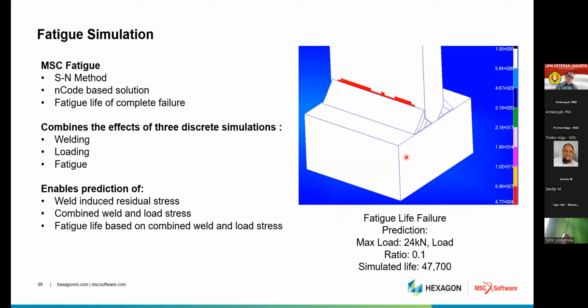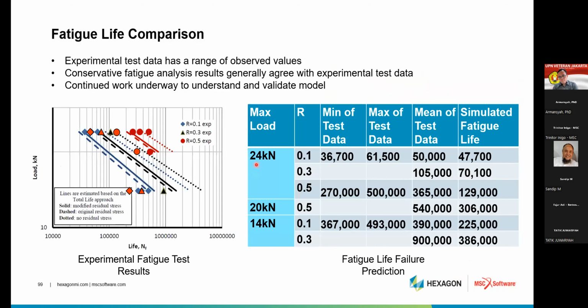So after these many cycles, the component will fail, or the crack or damage will happen in this particular area. Okay, and this is the comparison with the shop floor setup. For 24 kilonewton and R value 0.1, we have the mean of the test data and max of the test data. When we take the average of these two, it comes around 50,000, and the simulated life comes around 47,700 cycles. So it predicted very accurately in the software.